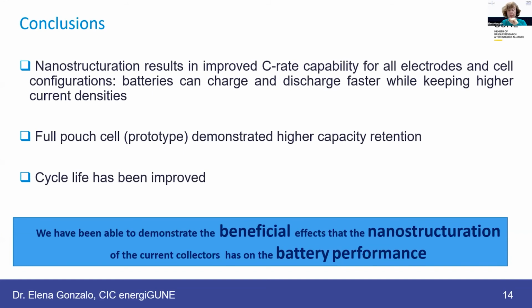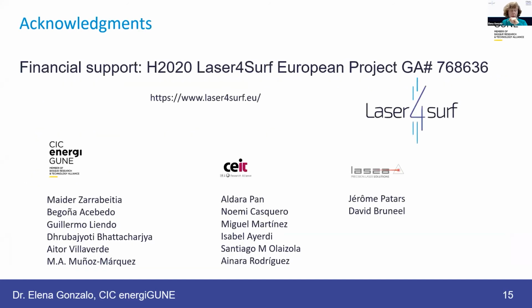Batteries can be charged and discharged faster while keeping the same or higher current densities. Our prototype, our full pouch cell, demonstrated higher capacity retention, and the cycle life was improved. I hope that we have been able to demonstrate the beneficial effect that the nanostructuration on current collector has on the battery performance of the batteries that we have tested.